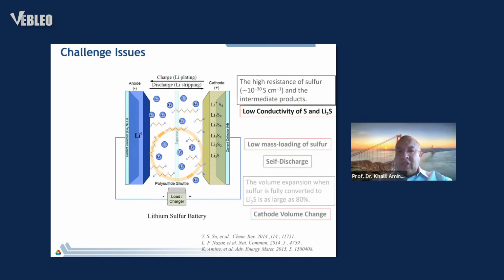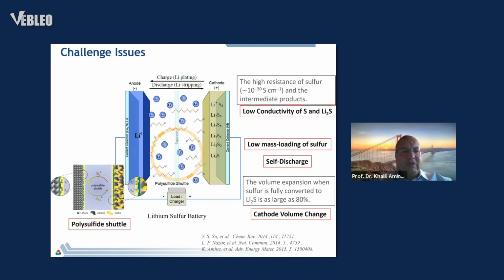The second one is actually low mass loading, because of expansion. When you react lithium with sulfur, you form Li2S, and then you have an 80% expansion that you really have to accommodate when you design your cell. The most difficult problems are basically the shuttle effect, or the dissolution of polysulfide, that lead to loss of active material. This one has not been fixed completely.